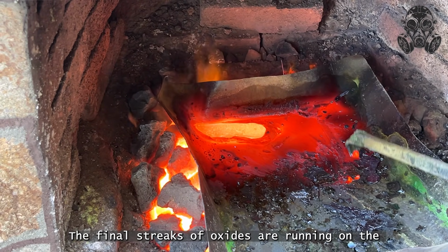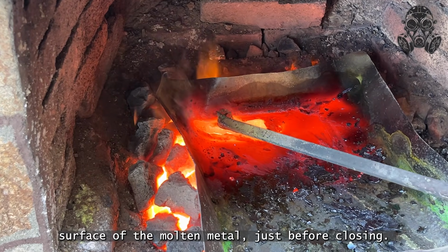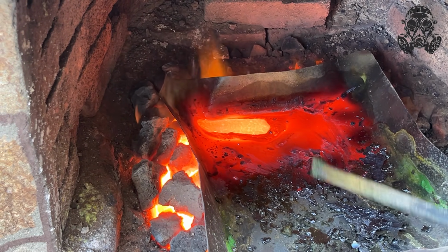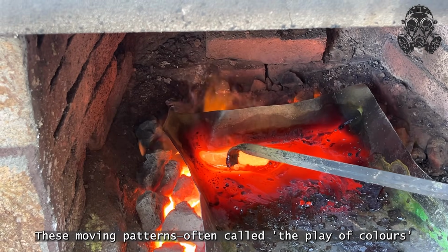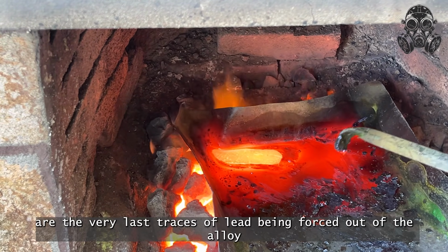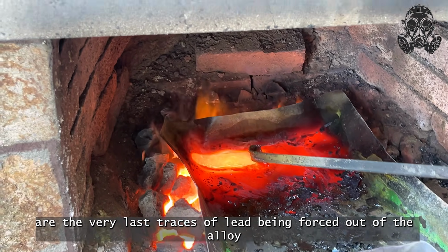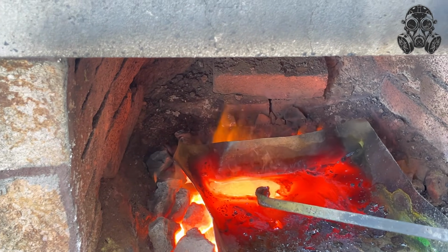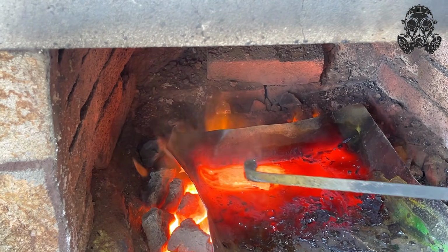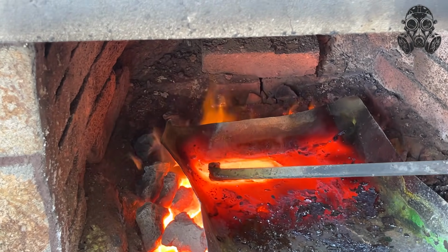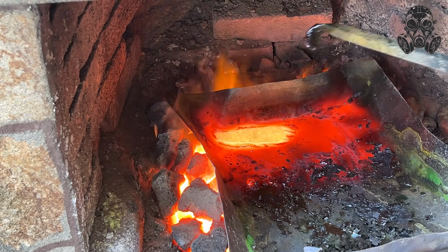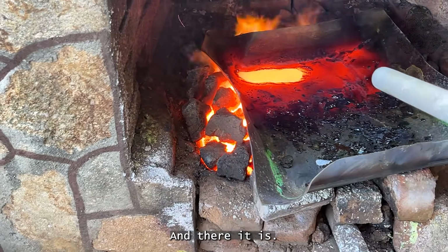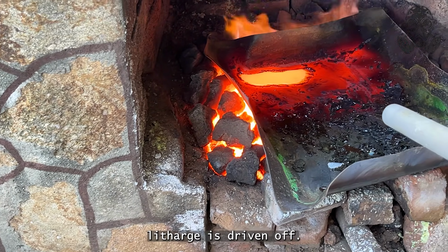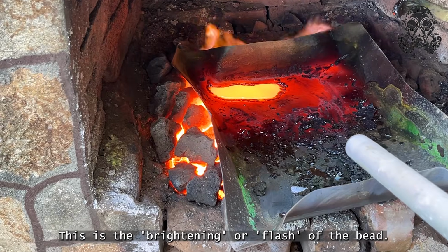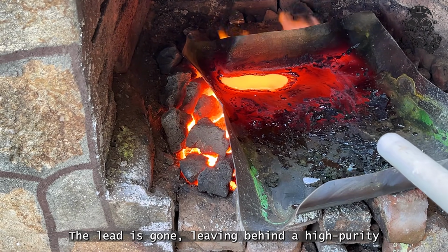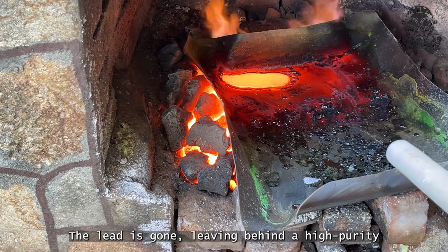The final streaks of oxides are running on the surface of the molten metal just before closing. These moving patterns, often called the play of colors, are the very last traces of lead being forced out of the alloy. And there it is. The surface clears instantly as the last of the litharge is driven off. This is the brightening or flash of the bead. The lead is gone, leaving behind a high-purity doré alloy of gold and silver.